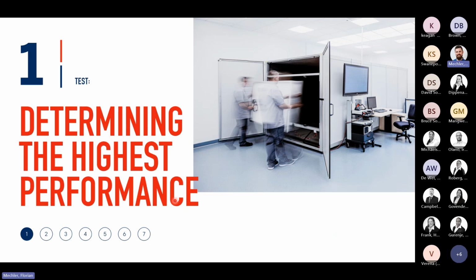One of the tests is determining the highest performance. So you can say it's a flasher test. We put the module like here into a dark room, and we give a flashlight, and then we see how much energy the module produces. And the flashlight brings 1000 watts, so it's a standard situation. And then we see if the module can really bring the watts which stand on the type plate.